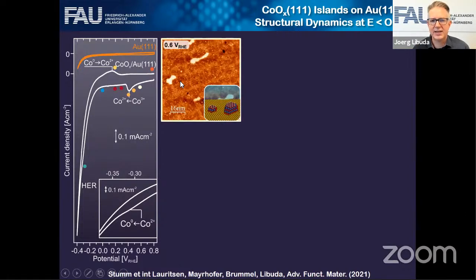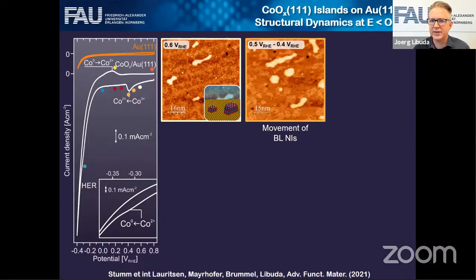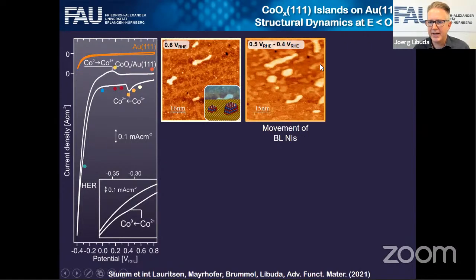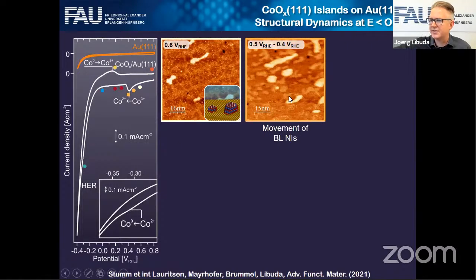And here you see a series of STM images. And you see these double bilayers, the white features here, and these darker features are the bilayer islands as a function of time. Of course, you don't have atomic resolution in this picture. It's very difficult. But you see that the structure is stable. Now we lower the potential and see what happens. And you see that these double bilayers are stable. But these bilayer islands seem to move as a function of time. So they really move over the surface in this region.